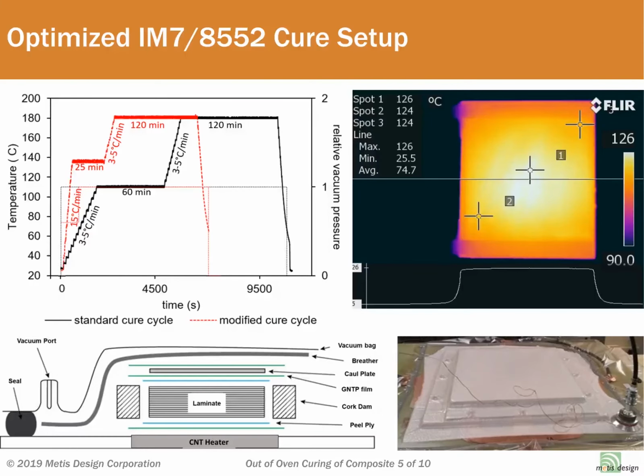So aside from being greener, why is this energy reduction significant? We have found multiple studies that have illustrated that the energy cost for operating an autoclave contributes to between 25 and 50% of the total fabricated cost of an aerospace composite part. So by reducing the energy by multiple orders of magnitude, that cost line item is effectively eliminated.